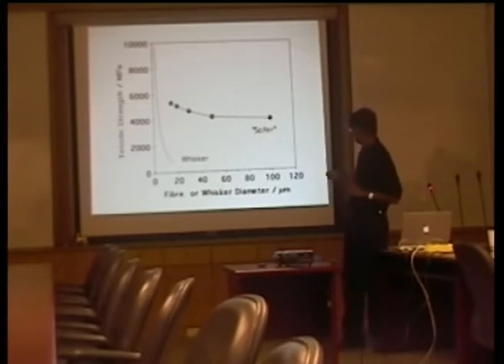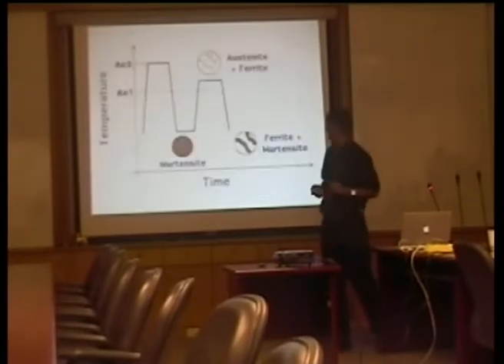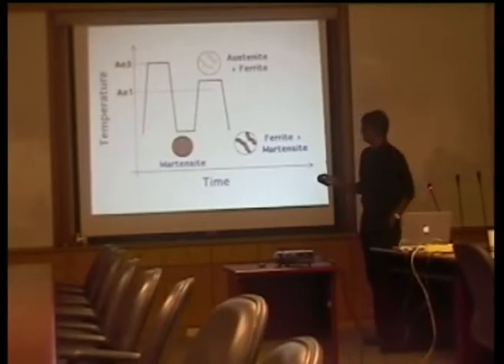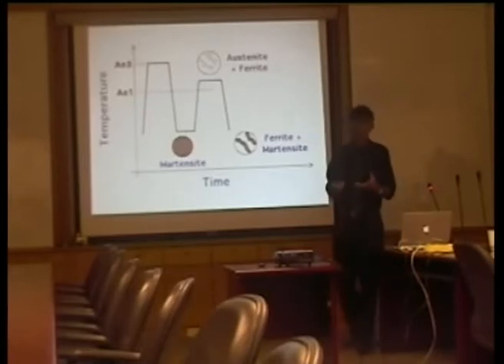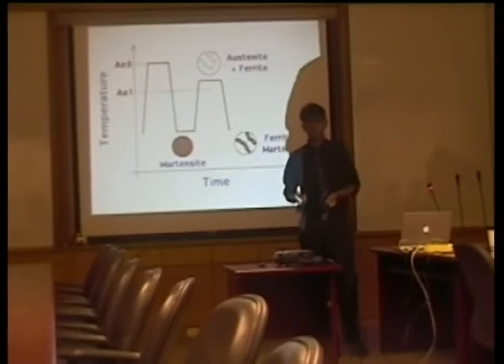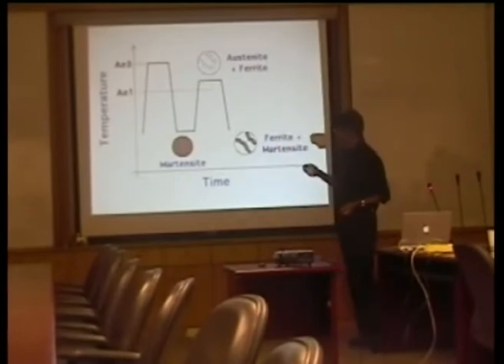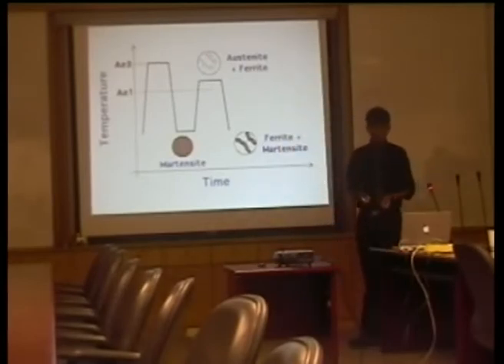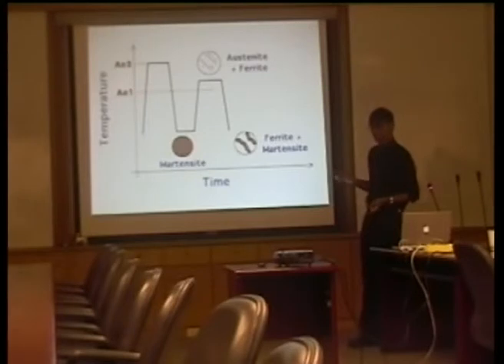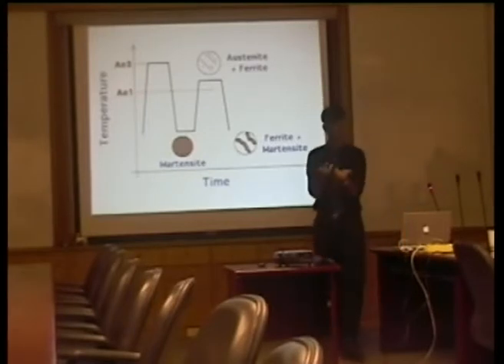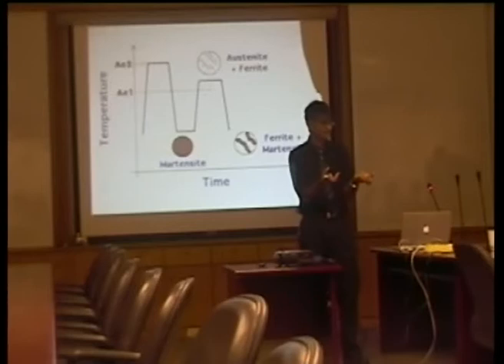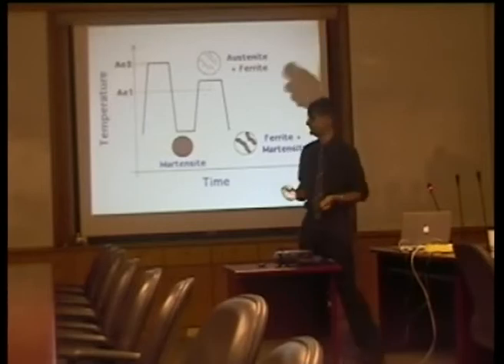So how is this wire actually made? Well, you start off by making a steel which is austenitic. So it's basically about 0.15 weight percent carbon, 1 manganese, 1 silicon. Austenitize it, quench it to martensite. You then raise the temperature again in between the Ae1 and Ae3 temperatures. That means you are in the two-phase field of austenite and ferrite. So that's intercritical annealing.